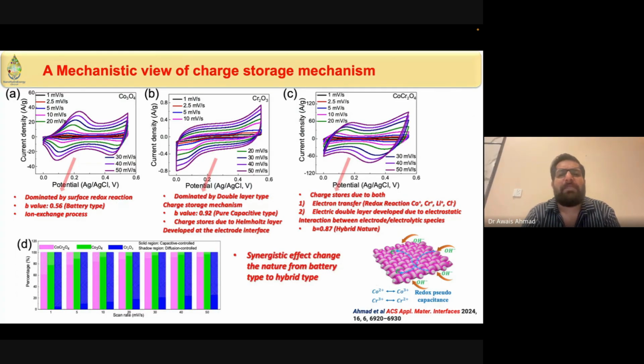Now, if we check the storage mechanism in this material, what was the interesting behavior? That we get all three types of material. We get pure capacitor, we get pure battery, and we get a new type of aqueous hybrid supercapacitor. So in the first, you can see here the cobalt reaction, which was dominated by surface redox reaction. You can see here and here, both are happening at the same time, oxidative and reductive reaction. So it is a battery type. And if you see this one, it is dominated by layered, because here you can see layer by layer. So it is dominated by double layer type. So it is known as pure capacitor.